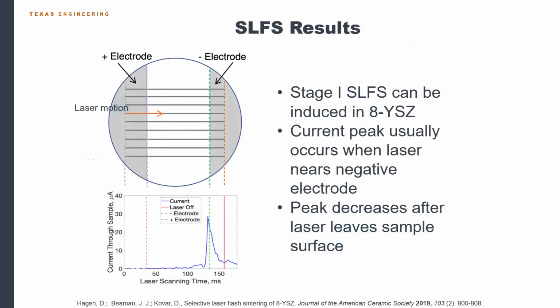The image on top is a top-down view of the powder bed. The gray regions are the electrodes, the white region is the loose powder, and the laser is indicated by the orange arrow. The laser starts scanning on the positive electrode. The plot below is the current through the powder bed as a function of time. As the laser starts scanning on the positive electrode, there's no current flowing, and it continues on into the powder bed. There's still no current flowing until just before it reaches the negative electrode, and then you see this sharp spike in current. This is the hallmark of successful laser flash sintering. Basically, the laser is heating the ceramic powder, increasing the electrical conductivity, and then you get current flowing. This is an adaptation of the flash sintering process in traditional ceramics.